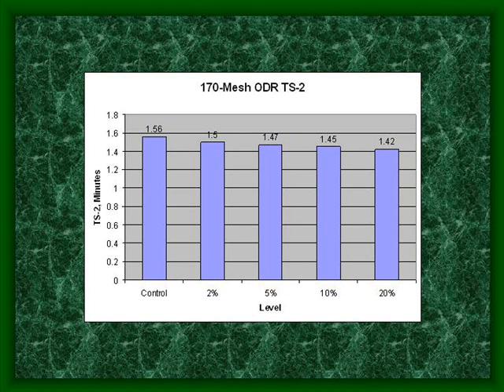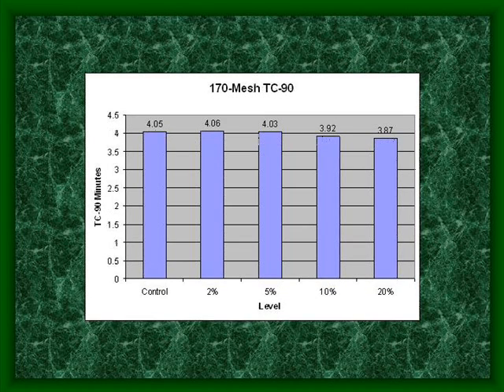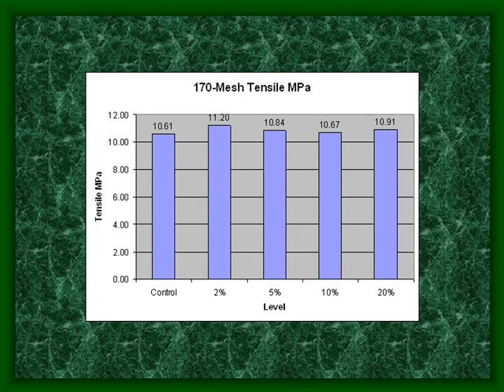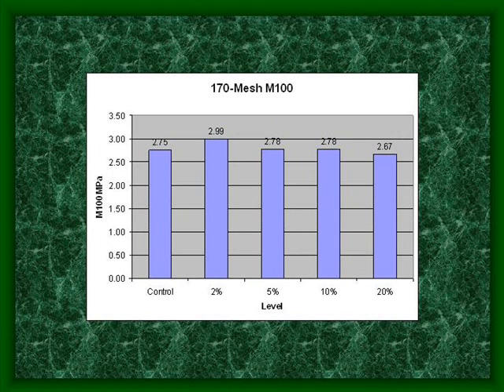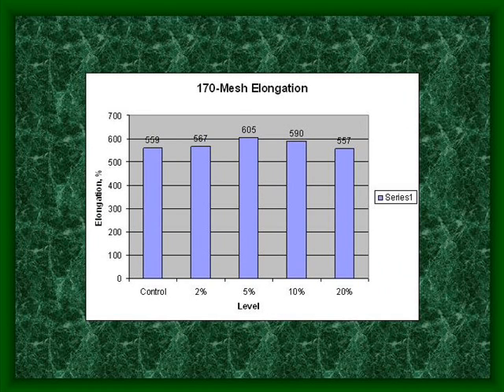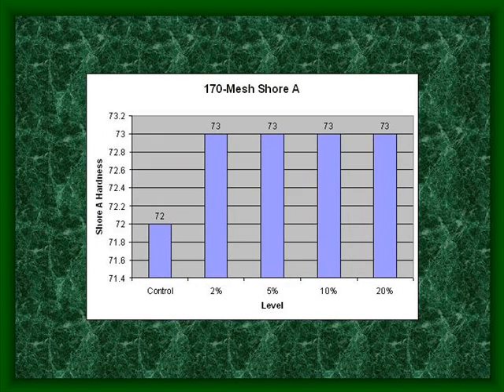There was a similar slight effect on TS2, with the higher viscosity samples giving the slightly faster TS2. And the cure rates were also slightly faster, which is consistent with the TS2 values. Tensile strength, once again, quite similar. Modulus, also minimal difference. Elongation, no difference among the samples. Hardness, the same results we got for the 80 mesh samples.